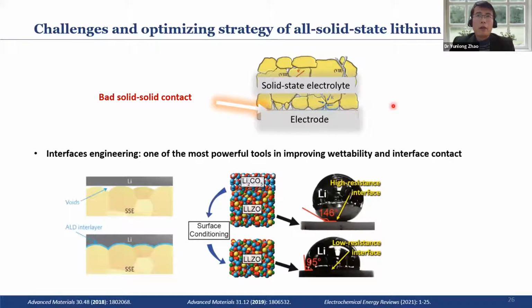One of the most powerful tools to improve the interface contact is interface engineering. For example, we can use ALD to create interlayers or some additional artificial surface coating to fill in these porous structures and make the interface smooth. In that case, they can have a lower resistance interface. You can see this is just after surface coating. If they use lithium metal as an anode, then the contact angle is significantly reduced, showing better wettability.